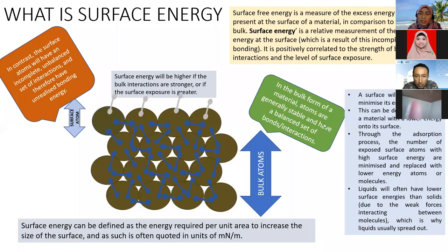This can be done by adsorbing a material with a lower energy onto its surface through the adsorption process. The number of exposed surface atoms with high surface energy are minimized and replaced with lower energy atoms or molecules. Liquids will often have lower surface energy than solids due to the weak forces between molecules, which is why liquids usually spread out. This is the understanding of surface energy. So we will go to another part.